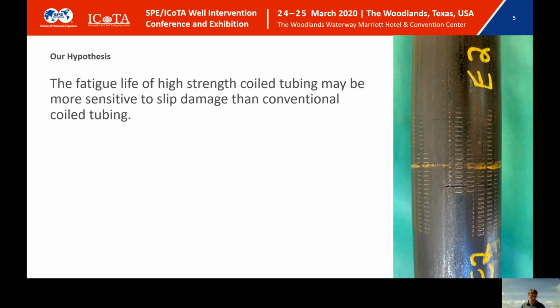Given that new strengths of coil tubing have higher yield strength, it follows that the hardness has also increased. We wondered if these new harder grades of coil were more susceptible to fatigue life degradation from slip marks and other mechanical damage than regular coil tubing that we've used in the past.